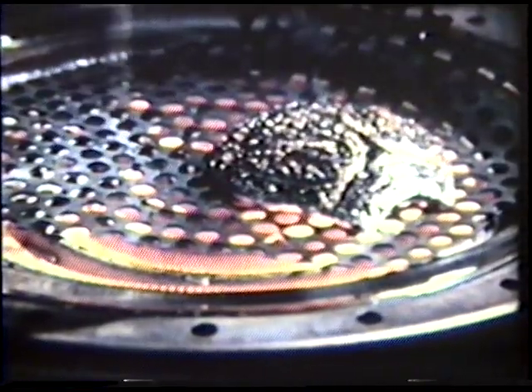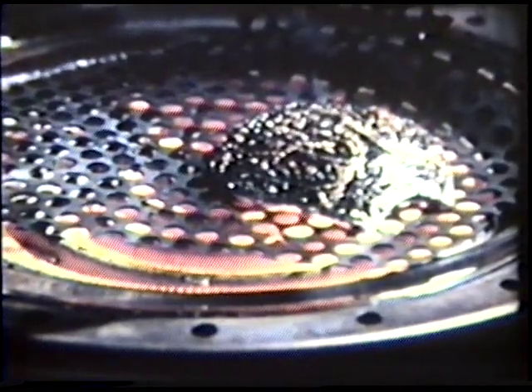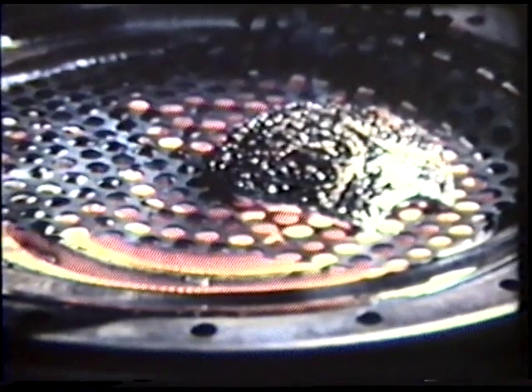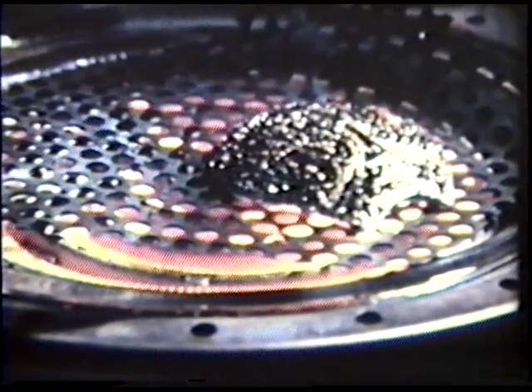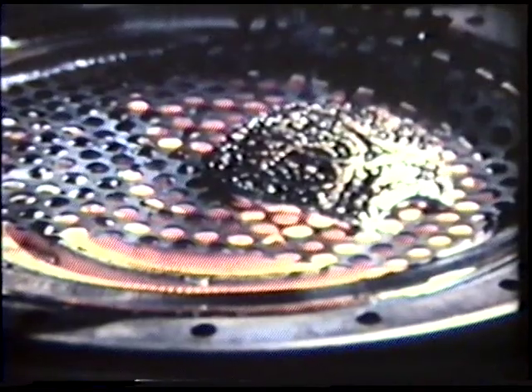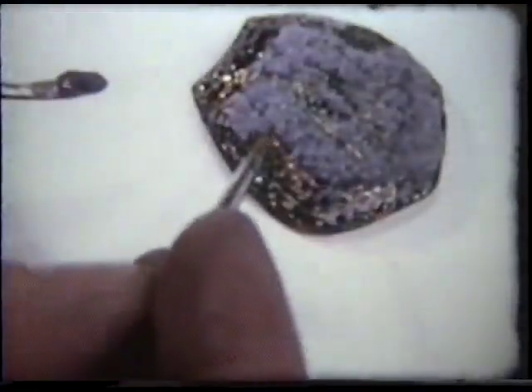The piece is dried and then placed in an electric kiln, in this case an electric hot plate with a Pyrex cover. At about 1400 degrees, the enamel becomes a layer of molten glass and loses most of the bulk of its previous state. A counter enamel on the underside overcomes the strains caused by the difference in expansion and contraction between the enamel and the gold. This difference is great enough that the gold is stretched to a slightly larger size as the enamel grips it on both sides while cooling.